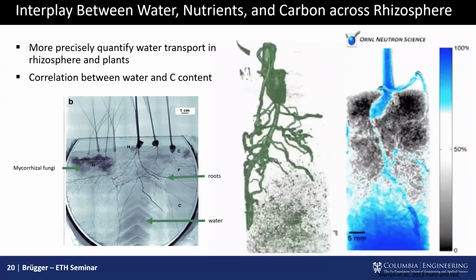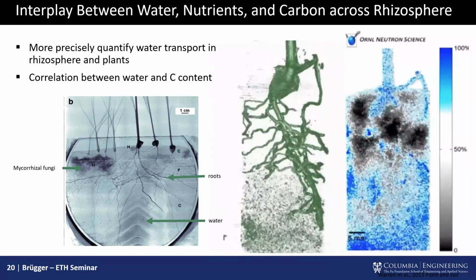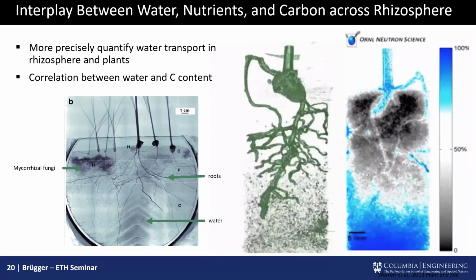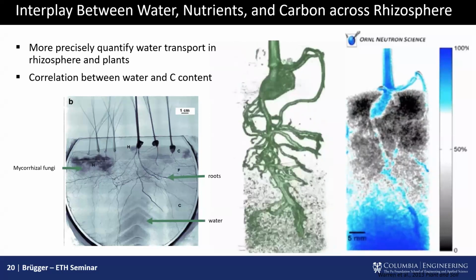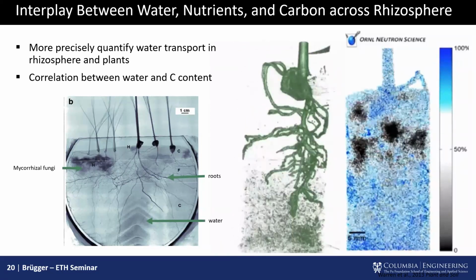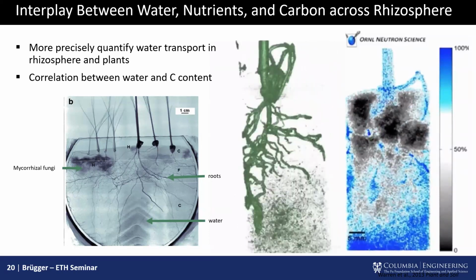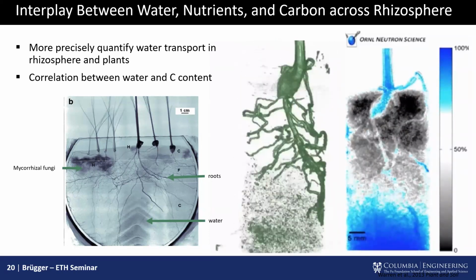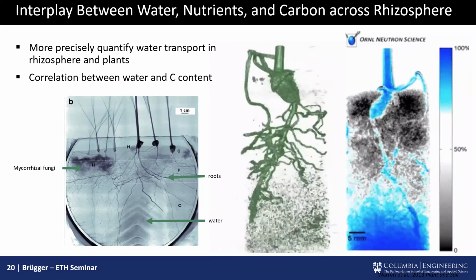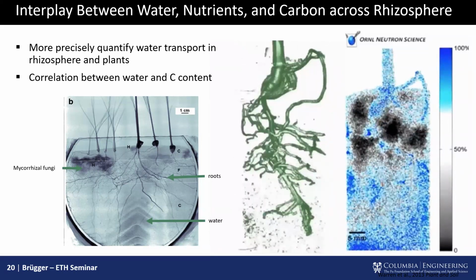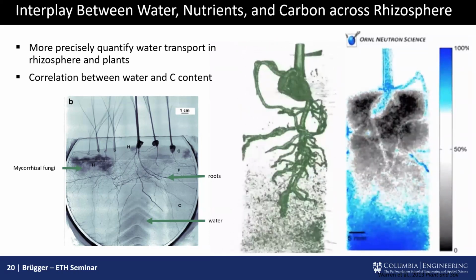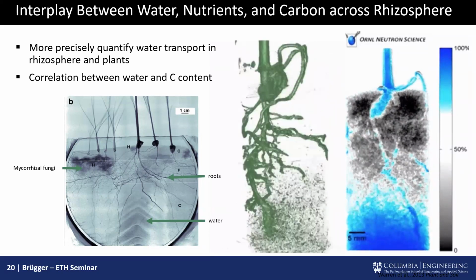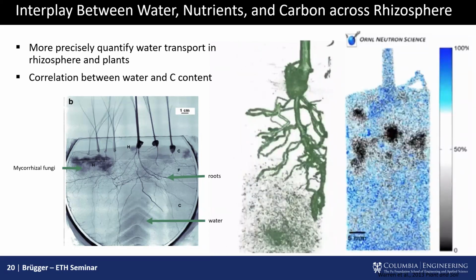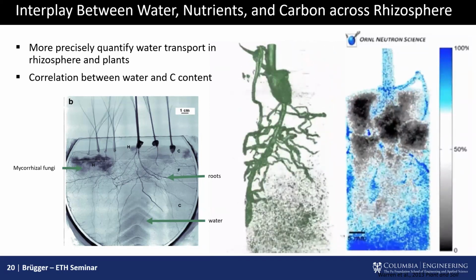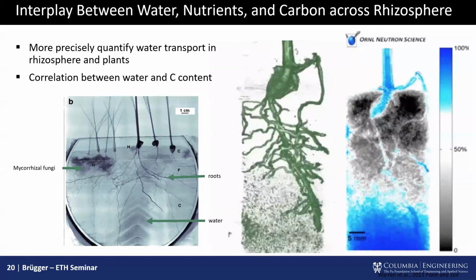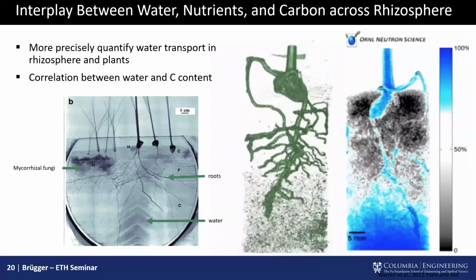And the beauty is, because neutrons in this case are either thermal or cold, there is no thermal activation of your sample. This plant had no idea it was in a neutron beam. If you put this in an X-ray beam, especially if it's low energy X-ray, it's counterintuitive, but you will literally catch this on fire in like 5 seconds and it will just combust and be gone. But with neutrons, your interaction with the plant is minimally invasive. Essentially, from a mechanical and chemical standpoint, it is zero. From a nuclear standpoint, you create unstable isotopes somewhere in the lattice, but from a mechanical standpoint, it's irrelevant.